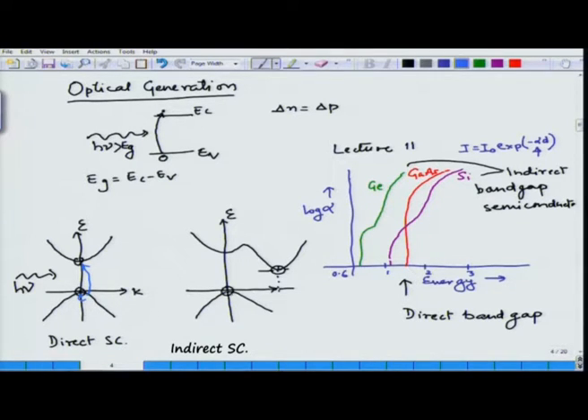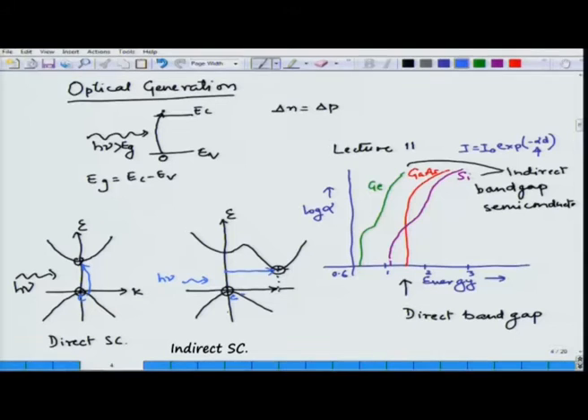On the other hand, when I try to absorb the same light which is higher than the band gap of this indirect band gap semiconductor, this electron can absorb the light, but it has no way of changing its crystal momentum, because the momentum of the photon which is coming in, or of the electrons, are both small. It needs to go from this value of momentum to the momentum of the minimum of the conduction band, and for that it requires assistance of a third particle, a phonon or thermal vibrations in this case, which have a very small amount of energy, but a large amount of momentum difference, and that process of